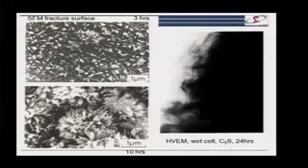Now, lots of people have said, oh, we now have these environmental electron microscopes that can solve this problem. And they don't, because if you have water present in an environmental microscope, all you see is the surface of the water. And if you remove that water in order to see what's underneath it, then you've dried it out. Okay? So even pictures in an environmental microscope are not radically different from that. They show these kind of little sea urchin or hedgehog structures, you know, which have some structure of CSH behind them.